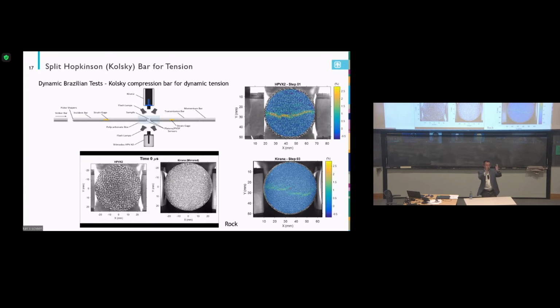We don't compress it this way, we put it sideways. If we compress sideways, it generates tension in the center. So you can see the center cracked and then opened. So at least it gave us some kind of tensile maximum, like a tensile strength. So this is the example for a rock. And again, we look at the surface, we load it sideways, and we see which side we're going to see the crack.